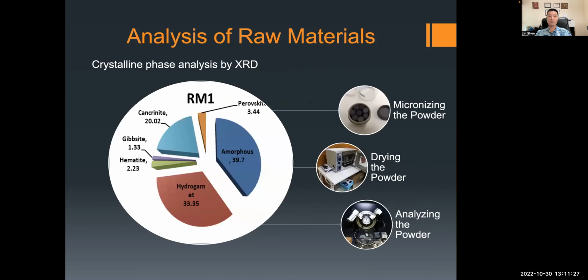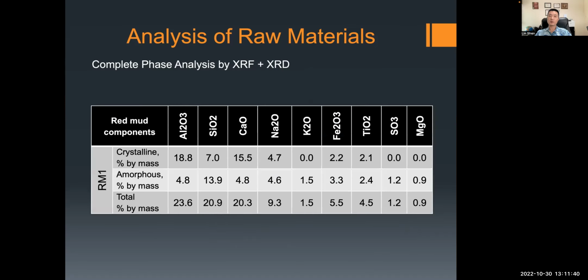We also use XRD, which is X-ray diffraction, to give us the idea of the percentage and type of crystalline phases. By combining XRD and XRF, we could have a much better estimation of the reactive phase and also the non-reactive phase. We also call that the amorphous phase and the crystalline phase, as well as the idea of the type and the strength of the crystalline phases.